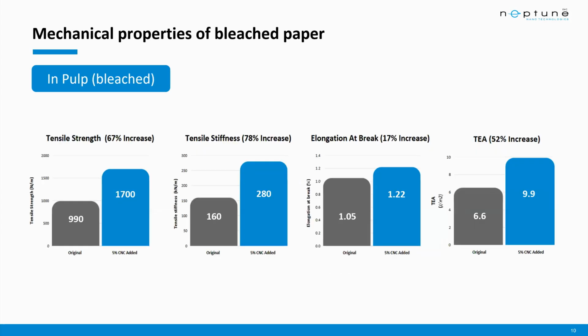So here we did quite a bit more testing, and this time it is in the bleached softwood pulp. And as you can see, this time we needed to bump up the CNC loading level a little bit higher to the 5% level. And then we tested for things like tensile strength, tensile stiffness, elongation at break, and tensile energy absorption. And as you can see, we see a very significant uplift in all of these categories, particularly in strength and stiffness, where the uplift is actually greater than 70%.